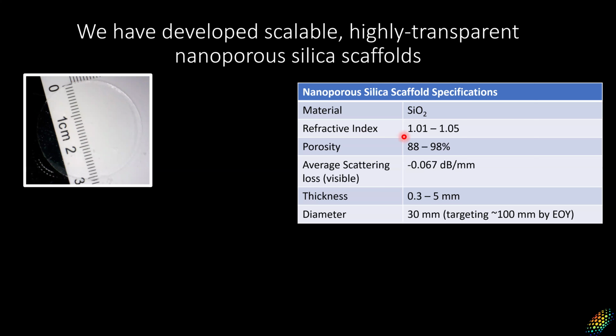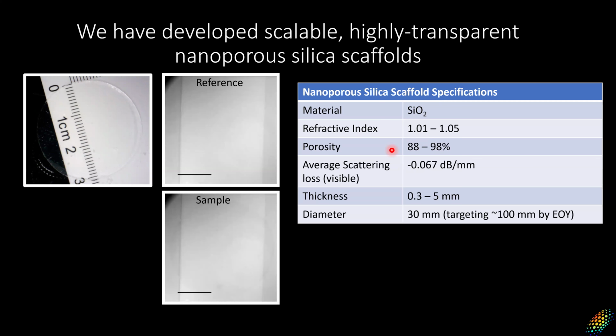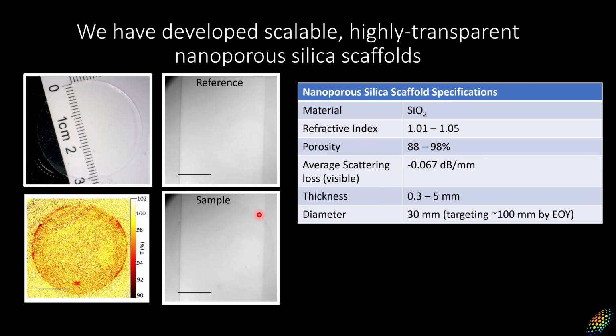We measure the refractive index directly. It can range, depending on how we make these, from about 1.01 to 1.05, and that corresponds to porosities of about 88 to 98%. And then we can measure loss by taking a picture with a reference, sticking the scaffold in there and looking at the difference between them. We get an average loss in the visible of roughly 0.067 dB per millimeter. This is at visible wavelengths. It's primarily from Rayleigh scattering. So as you go out to longer wavelengths, this decreases with the wavelength to the power of 4. So it becomes much, much lower as you go into the near and shortwave IR.